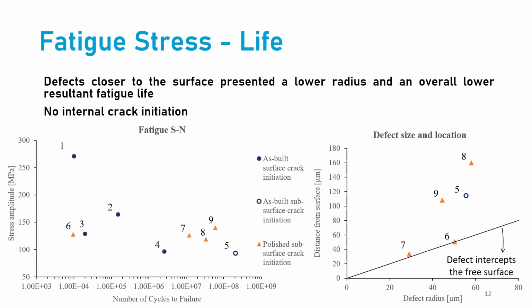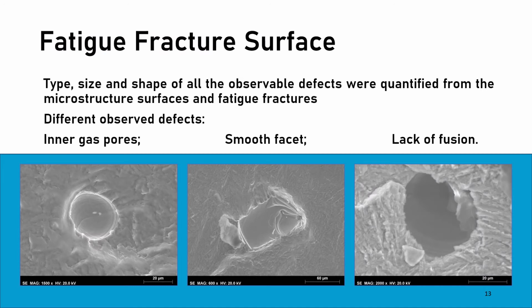From analysis of the distance to the surface and the radius of the defects responsible for subsurface crack initiation, we can clearly see that closest to the surface a lower radius was presented and an overall lower resultant fatigue life was obtained. We can see that especially when the defects intersect the free surface, there's a considerable reduction in fatigue life. Here the specimen 6, which intersects the free surface, has a considerably lower fatigue life than predicted. Now, what type of defects are present in the SLM samples?